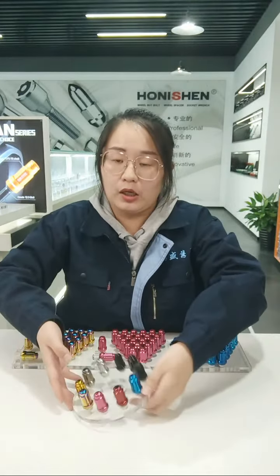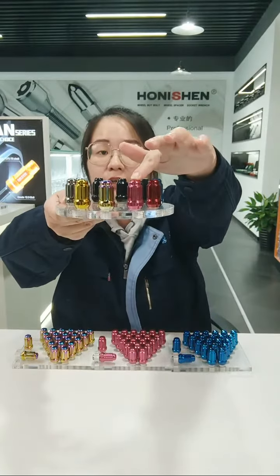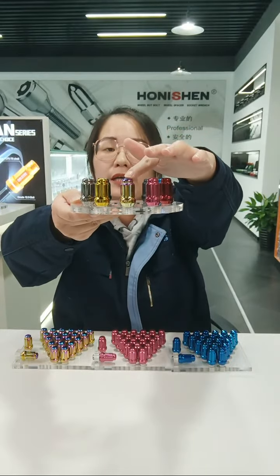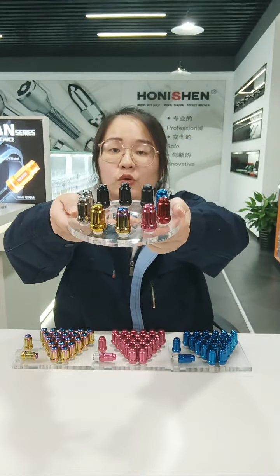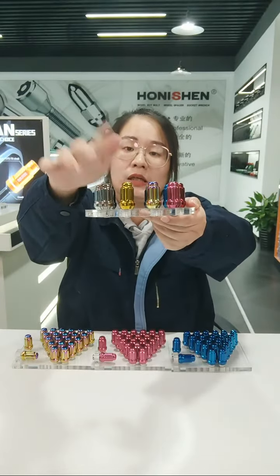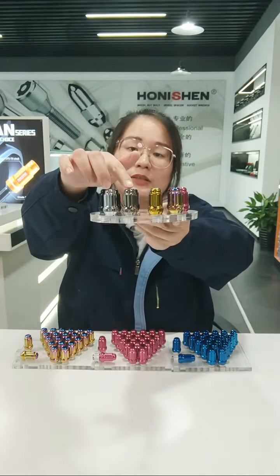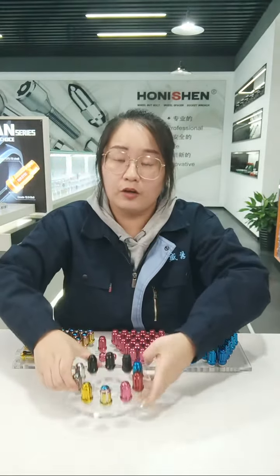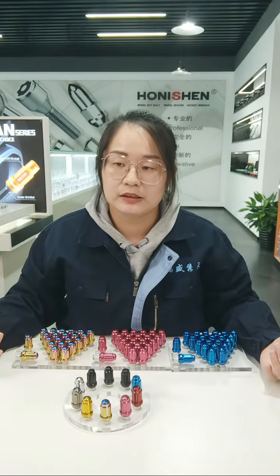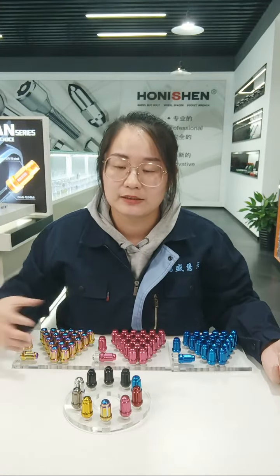We also have another plating, we call it titanium. For titanium, this is pink titanium, this is neochrome, we call it rainbow titanium. It looks like a rainbow. This is gold titanium and this is gray titanium. For titanium, the plating is very good. The color fastness is good and the anti-rust performance is very good. It could pass over 300 hours salt spray test.